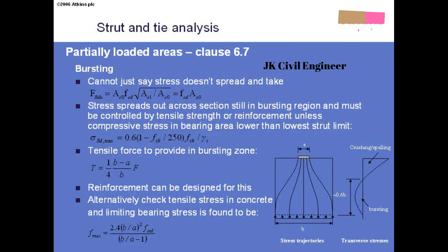or the code does allow us to utilize the tensile strength of the concrete to resist the splitting forces as well. So, coming back to this situation here, where we idealize the expanding flow of struts as a transverse tension, and we can use the formula early on to work out what that tensile force is. It's the expression here, quarter (B minus A) over B times F. We can either put in tension for that, or we can actually check whether the concrete in this height of 0.6B is able, working at its design tensile strength, to resist that splitting force.